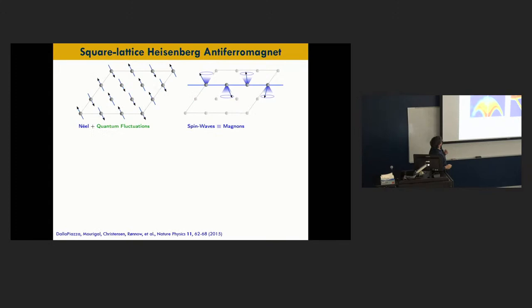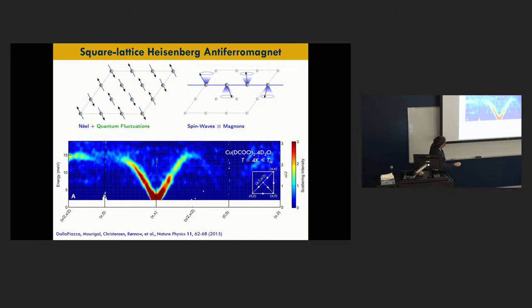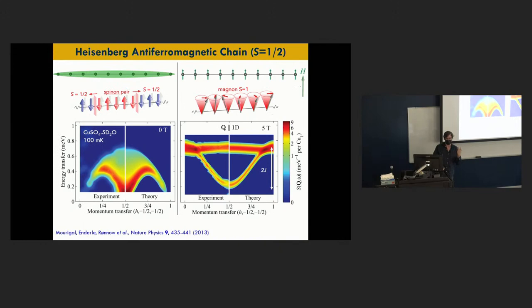Good. So just to convince you, here's another example that I worked on as a student. It's not a chain now, but a square lattice antiferromagnet. It has this kind of Neel state. And if you measure the magnetic excitations in the first Brillouin zone as a function of momentum and energy, what you see is well-defined, nicely defined branches. So it's a nice dispersion curve. This system is not entangled. There are just spin wave excitations, and it behaves as we expect. So something is very special in that material, and that's the fact that it's two-dimensional.